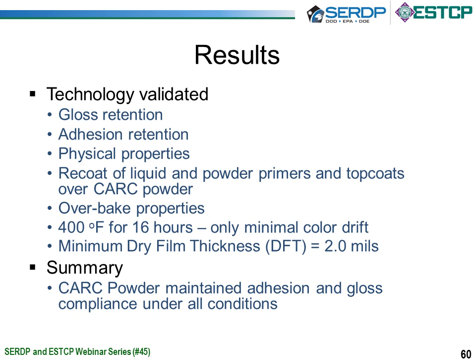What happens with overbake? A perfect example of that is we said you need a minimum of 10 minutes at 400 degrees metal temperature to achieve cure. We actually had a study where we left the coated panels in for 16 hours at 400 degrees. So if an oven shuts down and you go to lunch in a production line, what happens? We saw only a minimal color drift, and the drift was still within the allowed range of the specification.